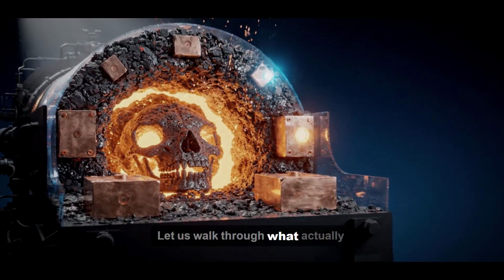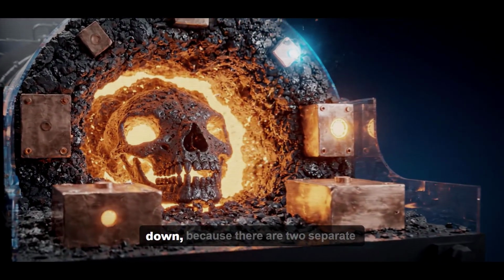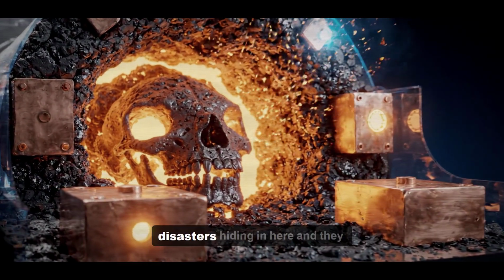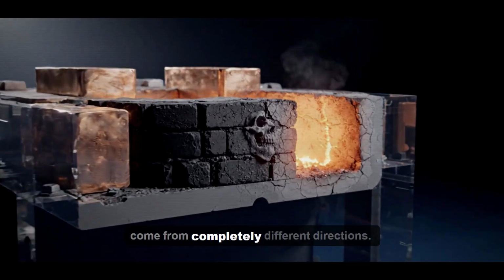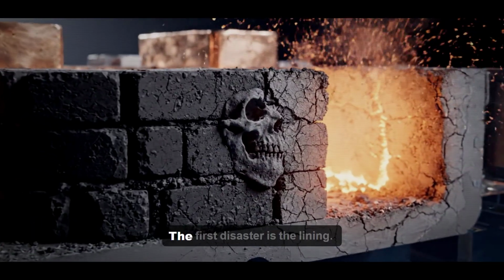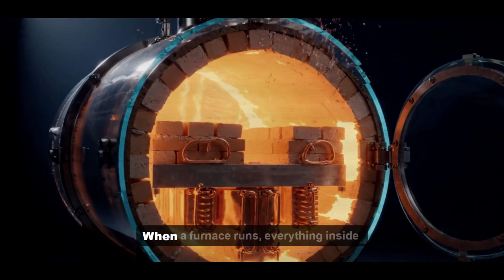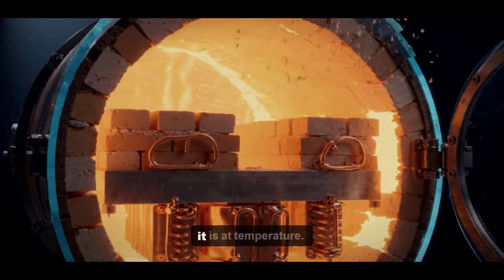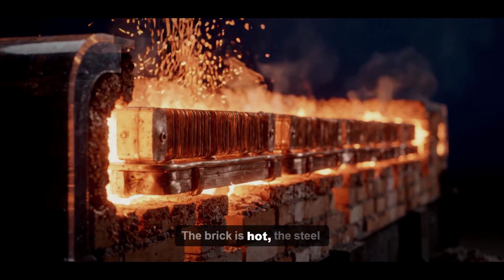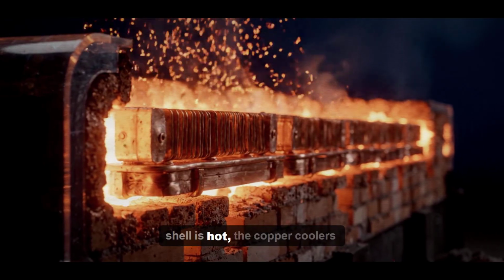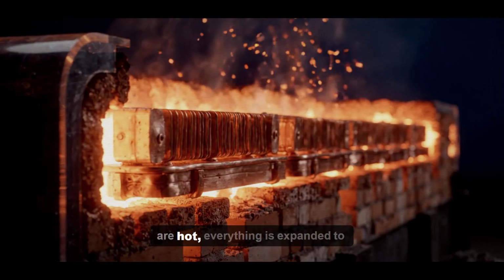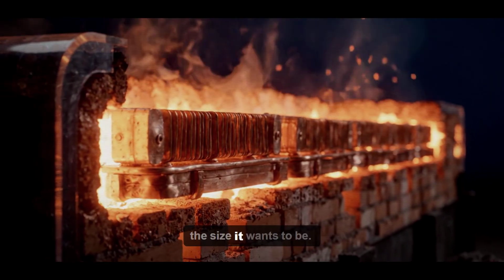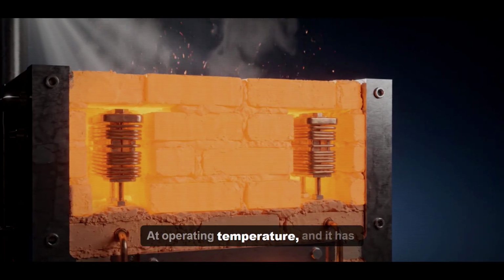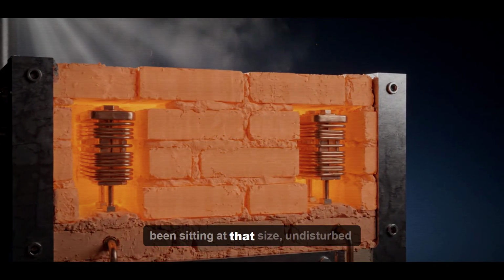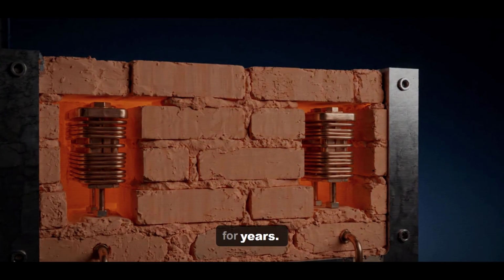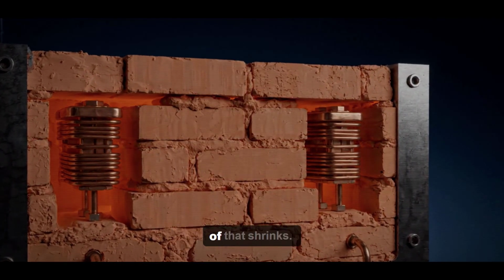Let us walk through what actually happens when one of these cools down, because there are two separate disasters hiding in here, and they come from completely different directions. The first disaster is the lining. When a furnace runs, everything inside it is at temperature. The brick is hot. The steel shell is hot. The copper coolers are hot. Everything has expanded to the size it wants to be, at operating temperature, and it has been sitting at that size, undisturbed, for years. When you cool it down, all of that shrinks.